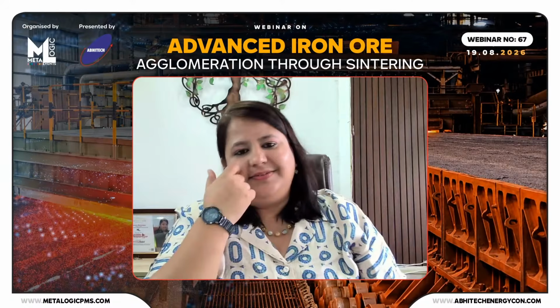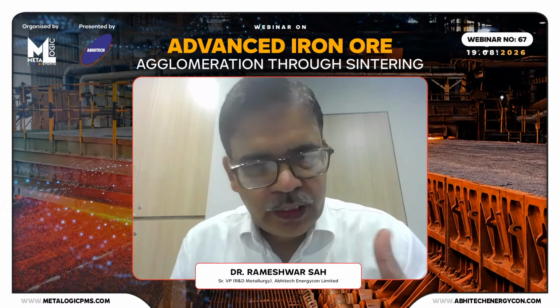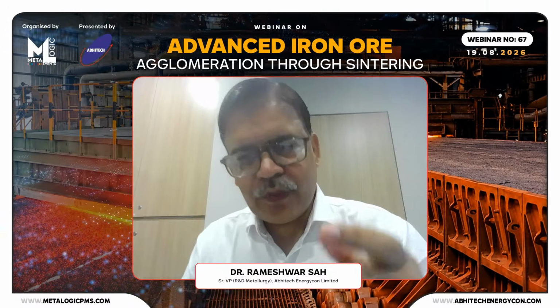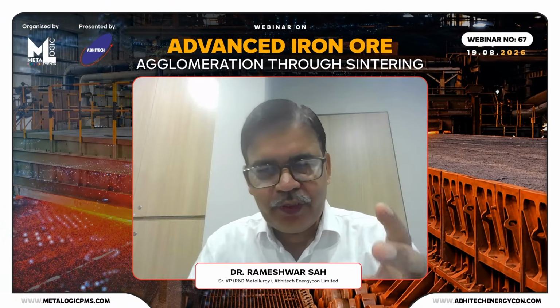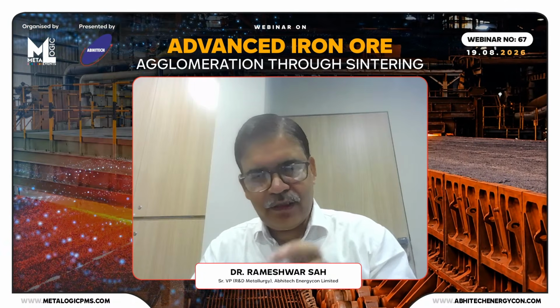Dr. Rameshwar, yeah. If I try to reframe the question, if it is low grade ore with Fe level 52, 53, the silica and alumina will be much higher. First, the alumina: if it goes beyond 3.5%, and this ore goes to sinter or even pellets, it is not good because it has a very detrimental effect over the process. So if alumina is more than 4%, 5, 6%, it has to undergo the beneficiation process.